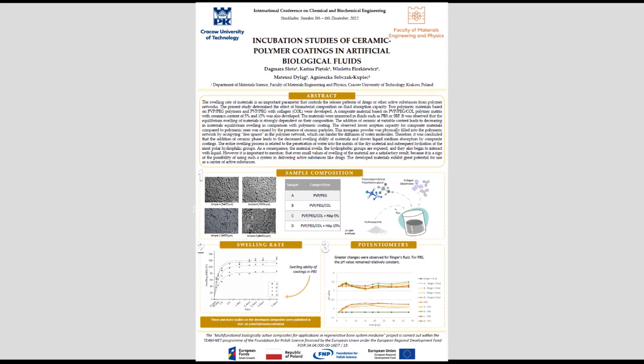And yeah, that was 37 degrees, as this temperature is similar to the temperature of the human body. And as you can see in the case of PBS, no large changes were observed. The values oscillated between 7.1 to, let's say, 7.5. So they can be considered relatively stable under the given condition. Larger changes were observed in the Ringer's fluid, where the values increased compared to the first day of the incubation.